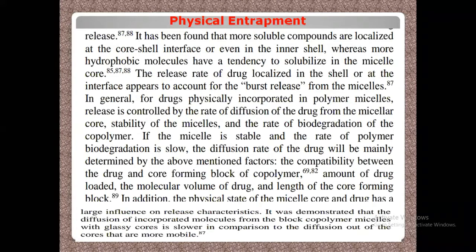In general, for drugs physically incorporated into polymer micelles, the release is controlled by the rate of diffusion of the drug from the micellar core, the stability of the micelles, and the rate of biodegradation of the copolymer. If the micelle is stable and the rate of polymer biodegradation is slow, the diffusion rate of the drug will be mainly determined by the compatibility between the drug and the core forming block of the copolymer, the amount of drug loaded, the molecular volume of the drug, and the length of the core forming block. All of these are factors which influence it.